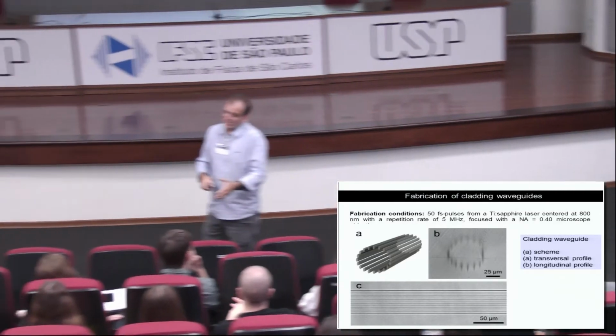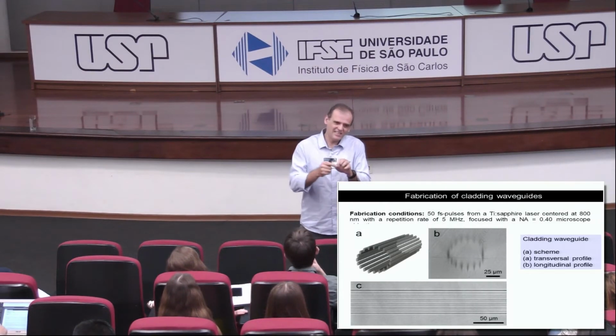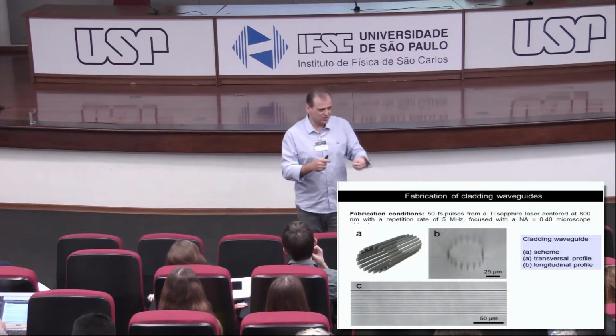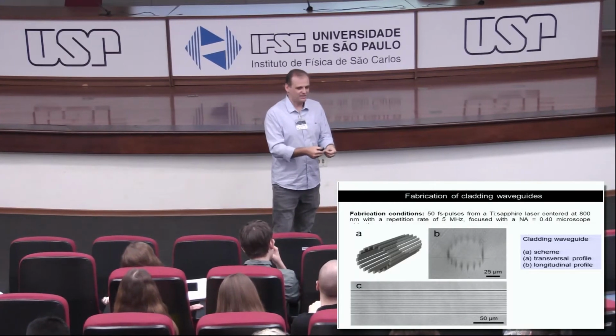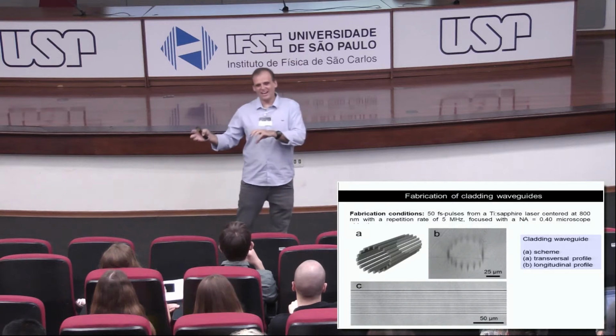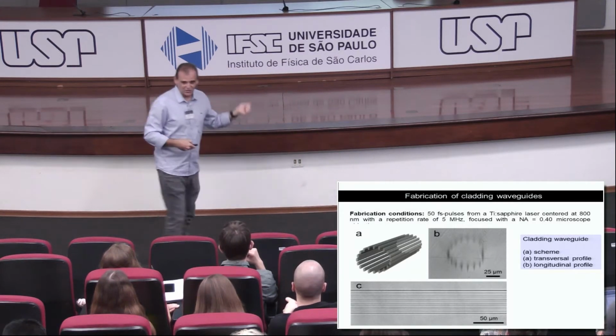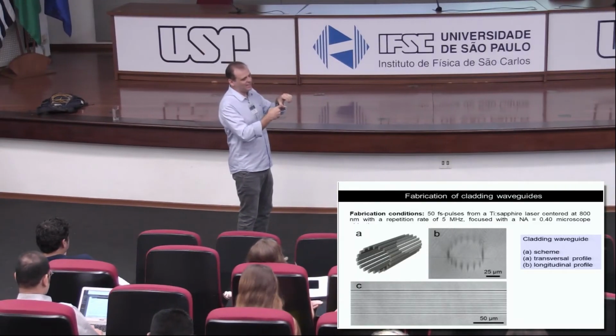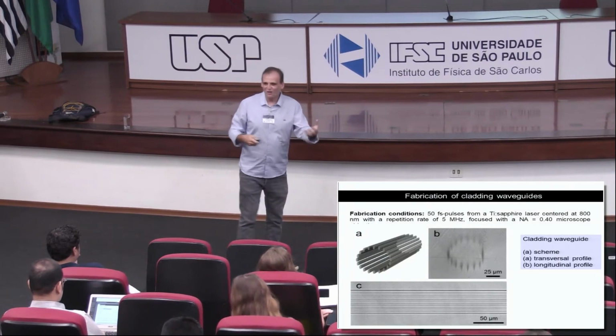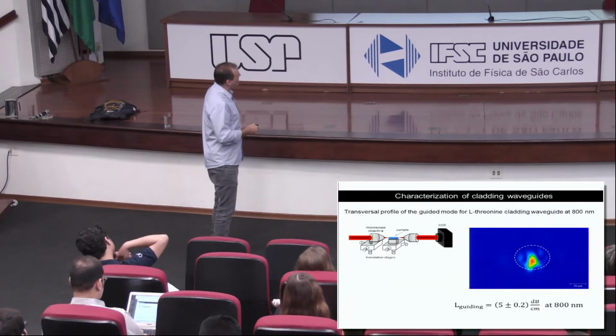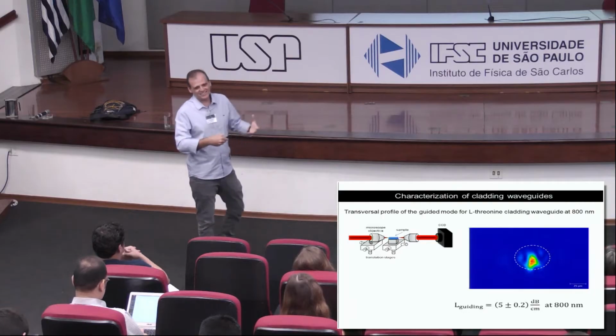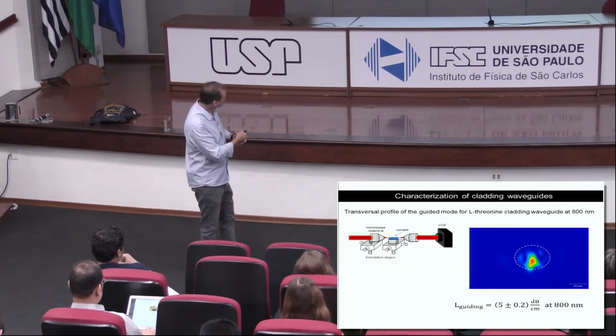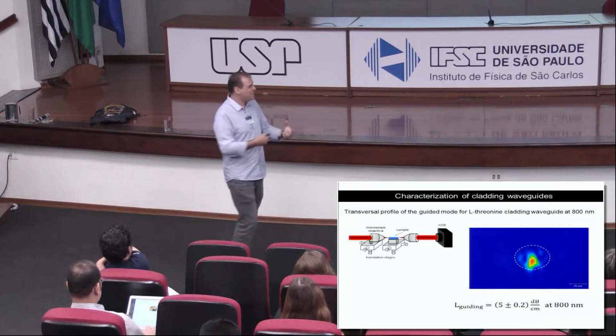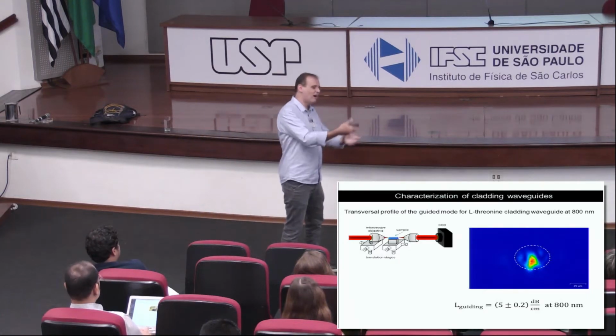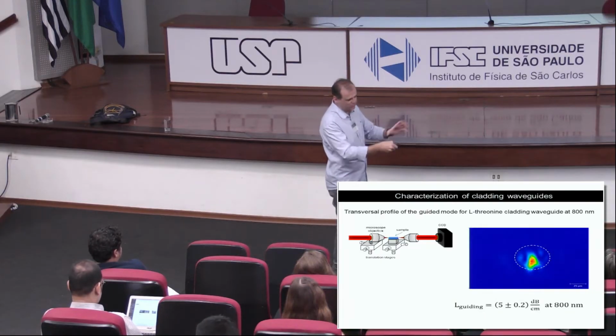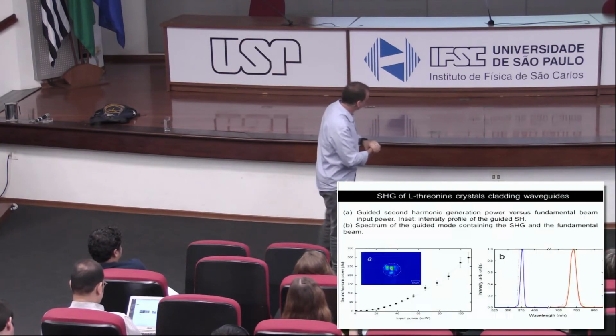Because in the Gorilla Glass, you can argue, okay, you are passing the laser, you are increasing the index of refraction, but you might be changing the material also, right? So that might not be the original Gorilla Glass. That might be something different. That's not the case here. So that's a good approach where you want to maintain the properties of the material, which is exactly the case for second harmonic generation. On the other hand, you don't get a very nice profile of guiding, right? But it's still okay. It's guiding light. You can engineer that a little if you wish. You can do some modeling and maybe try to find a better way to write this waveguide. But okay, it's still guiding.